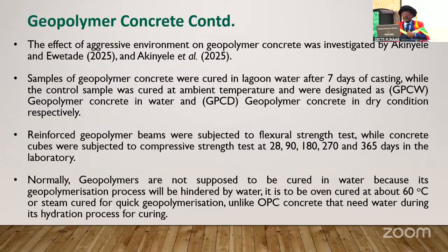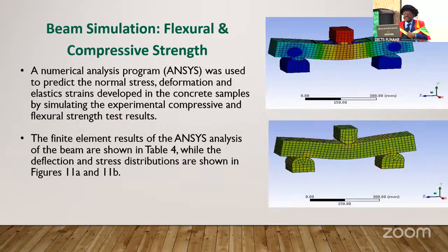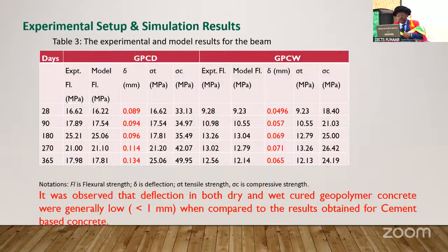We were able to carry out beam simulation also for the geopolymer concrete, and the result in table 3 shows the experimental result for our geopolymer concrete. For the deflection, for the one cured in water and dry, it was observed that the deflection in both dry and wet cured geopolymer concrete was generally low, below 1 mm. When compared to the result obtained for the cement-based concrete, we are having 3.5, and even one was about 32.2 or thereabout.